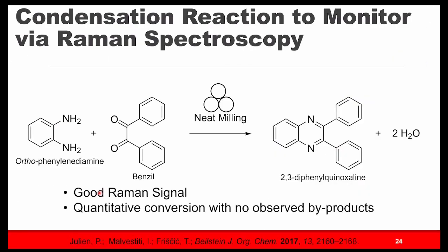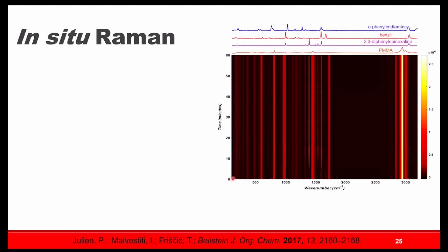In some work that I did subsequently, looking at temperature, we did this very simple condensation reaction, just grinding these two together. We're not adding any liquids in the transformation, just an amine coupling to make this quinoxaline with water as our only byproduct. This is a super nice reaction, gives a great signal, and we get quantitative conversion with no observed byproducts. So it really is wonderful chemistry.